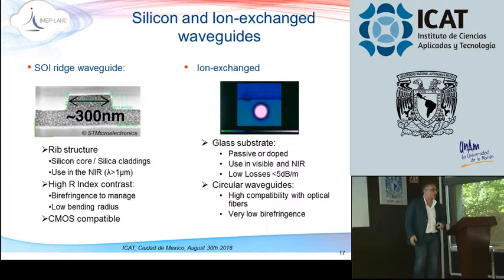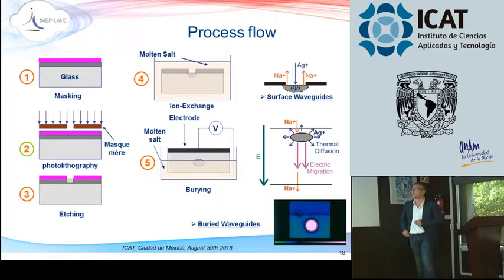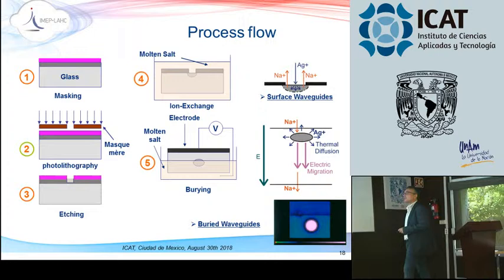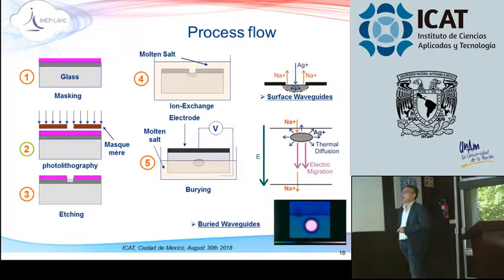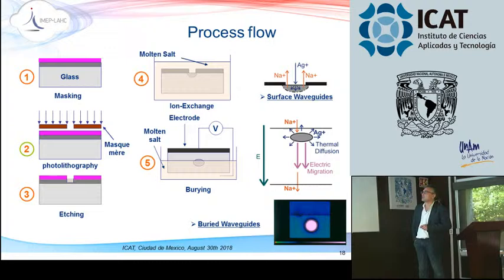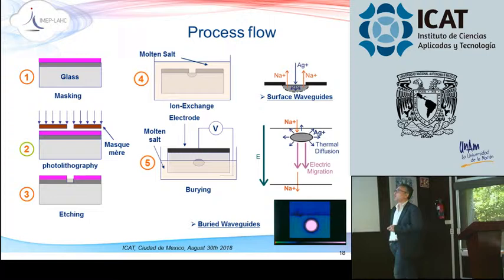So, how do we realize the waveguides in detail? We start from a glass on which we deposit a mask. This mask won't allow the ions to go through it. So then we create, by photolithography in the clean room, apertures in the mask. We just plunge this wafer inside of molten salt, where the ion exchange occurs. After it is done, you will create the core of the waveguide that is on the surface.